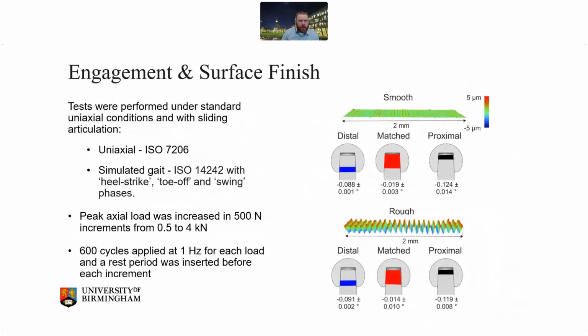And what we were interested in was comparing what is basically the industry standard at this point, a proximal engagement, since most tapers will be proximally engaged, compared to something more akin to a traditional Morse taper, or even a distal engagement. We did this by varying the taper angle of the male trunnion, and then just used fairly standard heads. But you have this industry standard proximal engagement, smooth tapers or rough tapers. The surface finish was targeted to be indicative of essentially commercially available products, whether it's smooth or what is referred to as a threaded one.